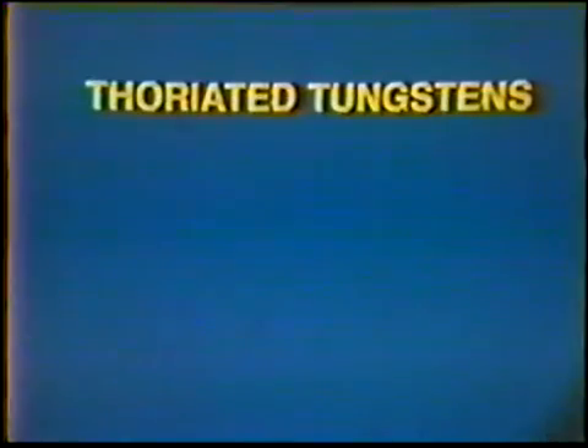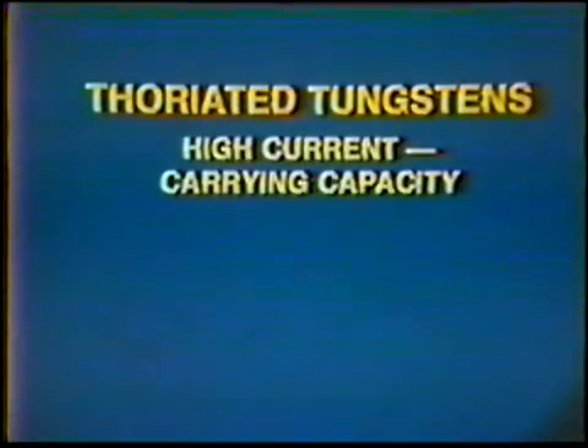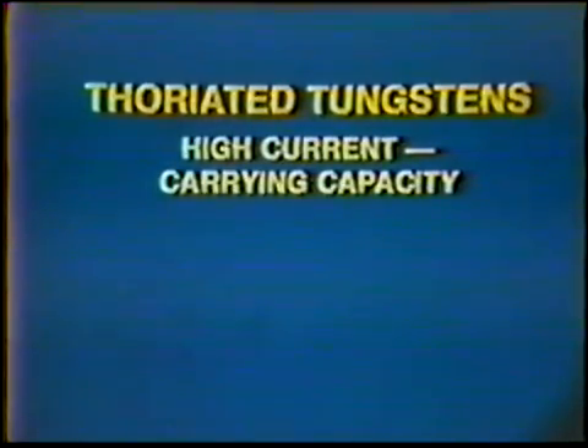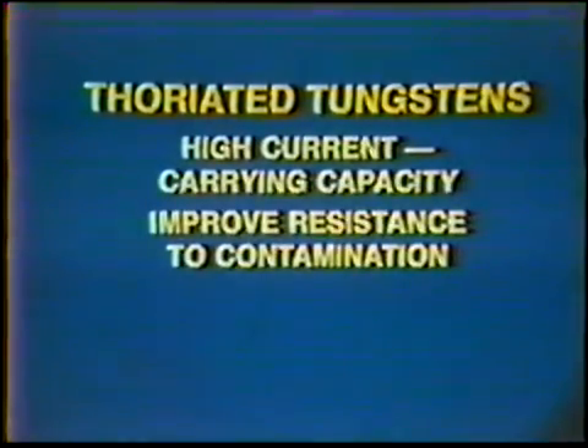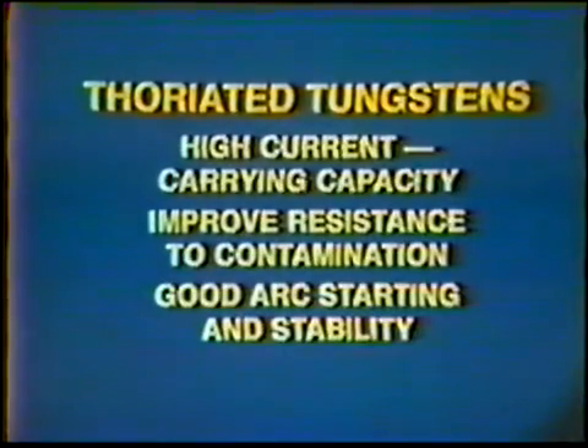1% and 2% thoriated tungstens are used with direct current. These tungstens are alloyed with a compound called thoria, which increases the current carrying capacity, provides longer life, and improves the resistance to contamination. Thoria also provides better arc starting and stability. The 2% thoriated tungstens possess these qualities to a higher degree than the 1%.